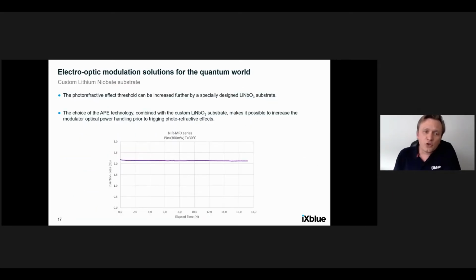In the next slide, we show improvements by using a different lithium niobate substrate that we specifically designed to increase the power handling of our modulators. So here we combine that with the process, and we show a graph where we have stable operation at 300 milliwatts of power at 1064 nanometer in this case, at basically room temperature. So that's another factor that increases our power handling and stability of the product.